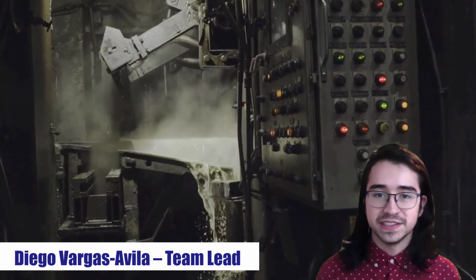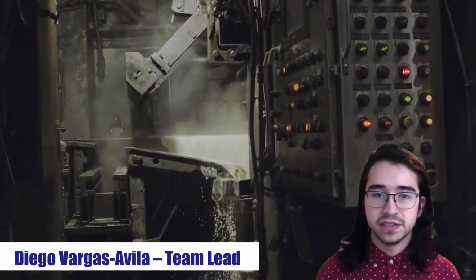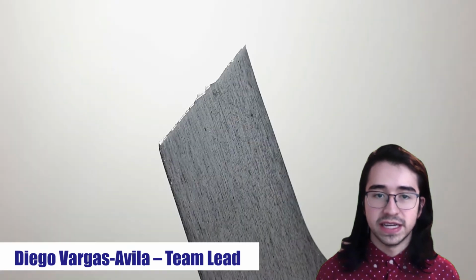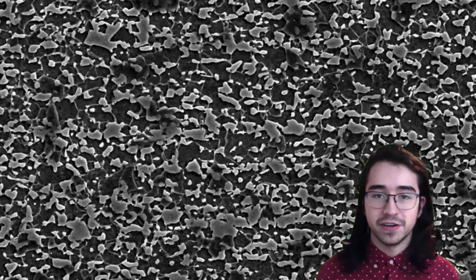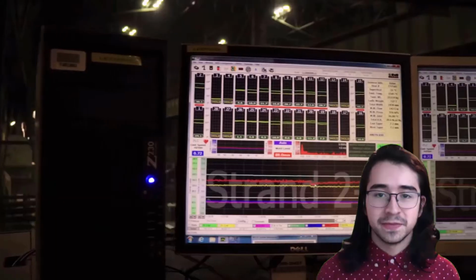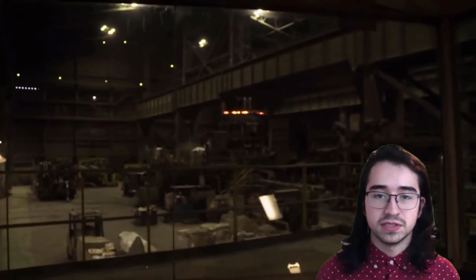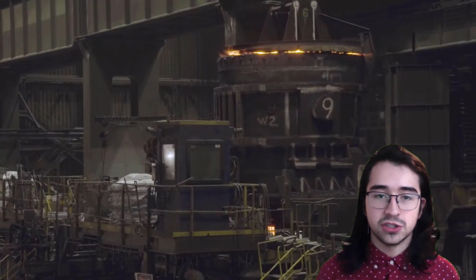Given the project constraints, the changes which can be implemented are limited to the furnace temperature and the speed of the coil. Through analysis of current plant data and our samples, it was concluded that the amount of ferrite in the steel should be increased. This is achieved by decreasing the intercritical annealing temperature and the coil speed. Although outside the scope of this project, it is also recommended that Stelco adjust their steel chemistry for future work to enhance heat treatment operations and mitigate centerline segregation.